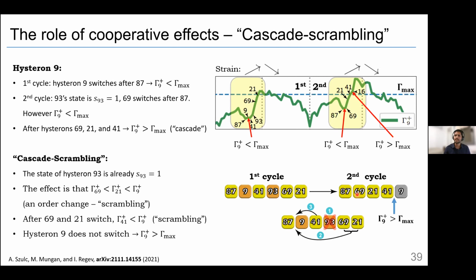And the effect we call cascade scrambling. If we look a little bit closer, you can see that the original sequence is 87, 9, 41, 93, 69, and 21. And what happens, because if you remember, 93 was frozen here, so it cannot switch. Here it is already in state S=1, it cannot switch again, so it is not here. And what happens is 69 and 21 are pushed before 9. And after that, 41 is also pushed before 9, and 9 cannot switch. So this effect of scrambling of the cascade is what causes hysteron 9 to do the threshold oscillations.